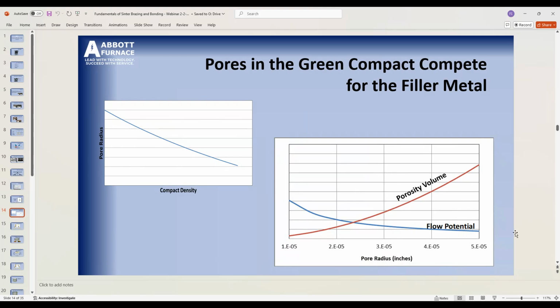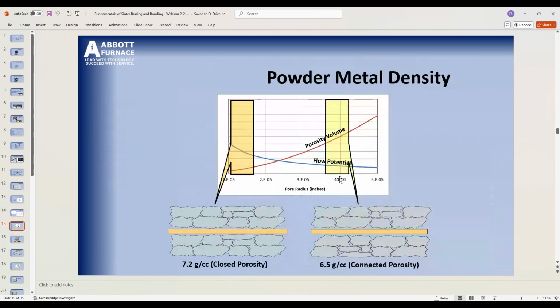Okay, so how do we stop this, right? Well, if we look at this, here's our plot of our flow, it wanting to steal it versus the volume. Okay, and you see at a real high density, we're down here. So it's really not going to steal a whole lot, but it's got a pretty strong tendency to flow, right? Or the capillary action is pretty high. But down over here in our 6.5 or so, the tendency is low, but there's a lot of volume in that porosity that you can fill. And so what that means is, okay, in a conventional process, you'd look at it and say, well, that's not a big deal. It's not going to happen that fast, but you're going to sinter. So we're going to be at this brazing temperature and this sintering temperature for like 20 to 30 minutes. We've got all the time in the world for it to suck all of this filler metal in. Okay, so it's really important. We got to look at, well, how do we stop this?